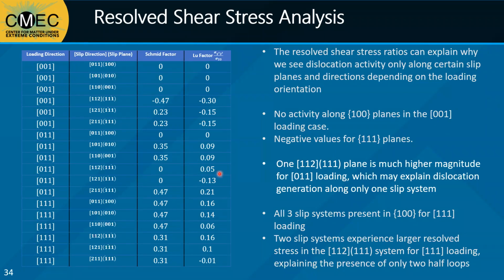However, for the 011 case, we do see activity along one slip plane. We can see that for the 211 plane in the 011 loading case, one of these slip planes has a much higher Liu factor compared to the other two, where one is negative and one is just smaller in magnitude. This could explain why we see only one slip system active in the 011 compression case. Finally, for the 111 loading direction, we saw activity in all three of the 100 planes. We can see that all three values of these are positive, although one is smaller than the other, but the 111 loading case had a smaller defect threshold for all the pressures, which could explain why we still see this one occurring compared to the lack of activity in the 011 case.